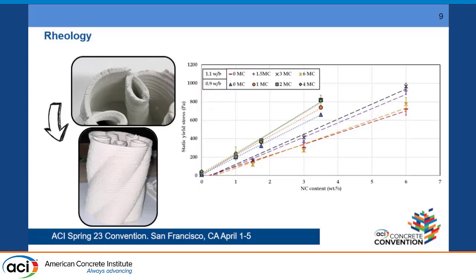So rheologically, if you look at the static yield stress, there's very little gain, and in some cases you would see a detriment to adding something like a viscosity modifying admixture. However, in the realm of 3D printing performance, instead of printing with a solid material, so when it's being extruded, I'm not extruding as a solid region, I actually can deposit it in a liquid form and then let it act as a solid afterwards. And that drops the stiffness of the material as it's being extruded, meaning I end up with better filaments.